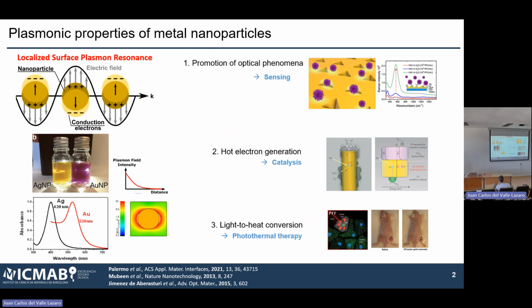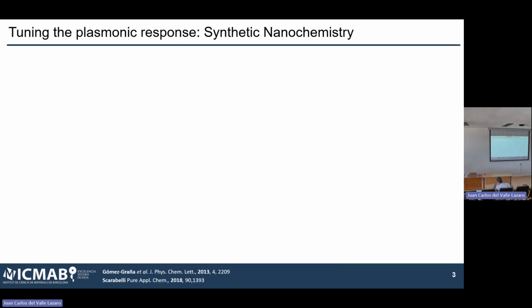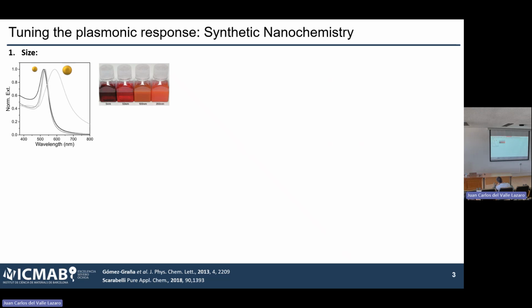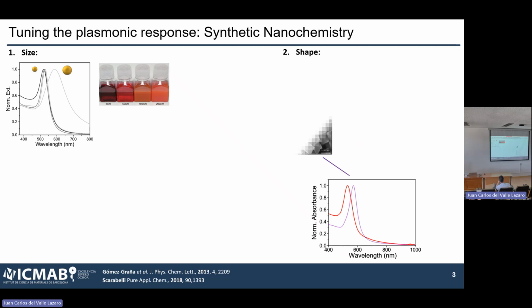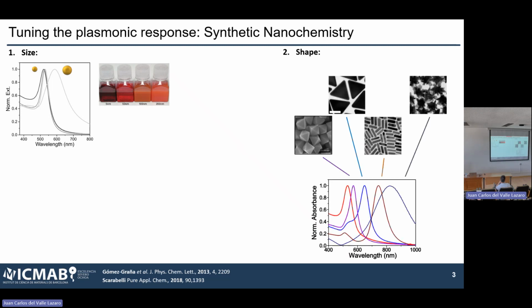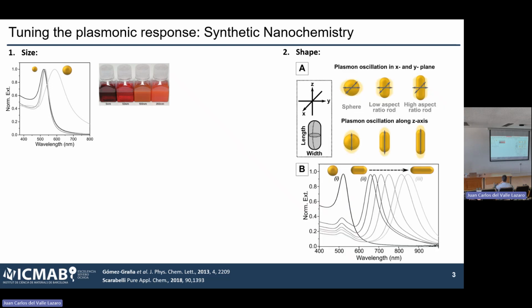So there is a lot of interest in this type of structures, and in colloidal chemistry we got very, very good at tuning this plasmonic response. It turned out that the optical response of the nanoparticle can be modified by changing the nanoparticle size, as you can see here, red shifting, so moving towards lower energy when the particle gets bigger. We can play with the shape of the particles, and again tune the response.